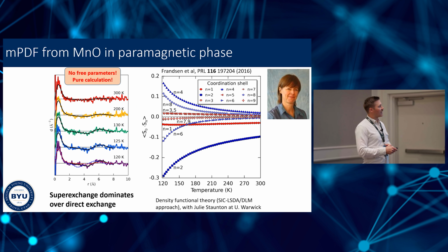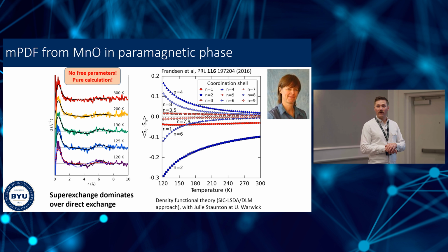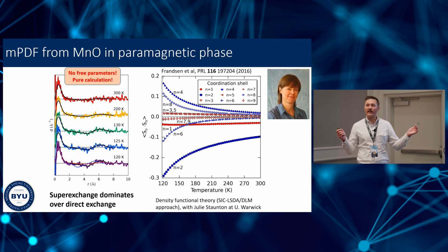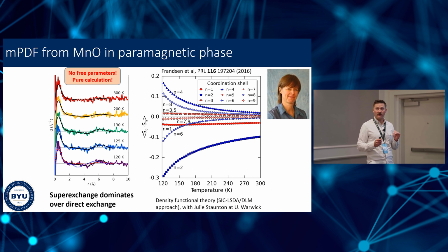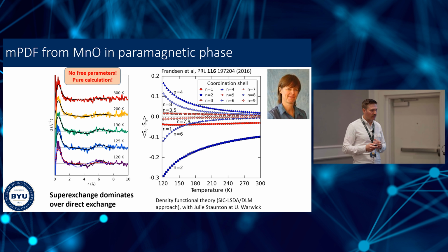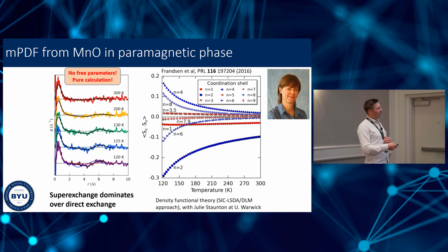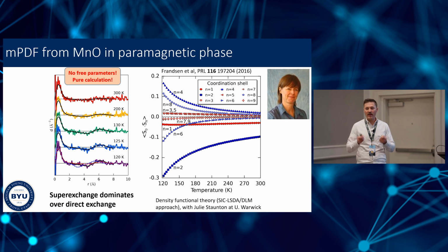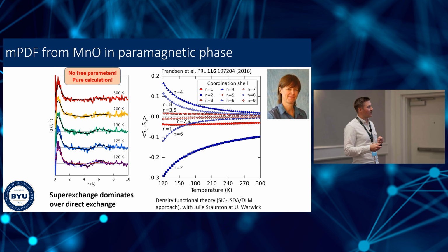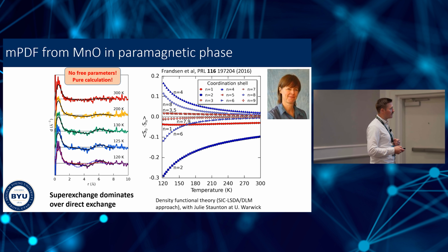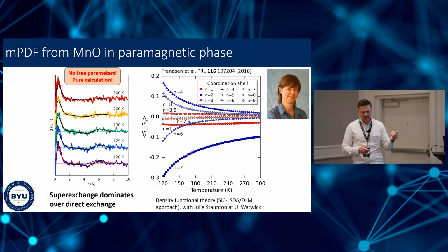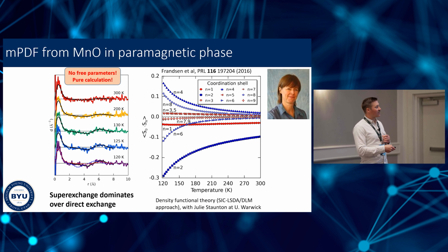But more interesting was to look at the magnetic PDF signal above the Néel temperature, where there were no longer any magnetic Bragg peaks in the scattering pattern. There was magnetic diffuse scattering, of course, because we do have short-range magnetic correlations. But now we can look at those short-range correlations in real space. And so here's the magnetic PDF, these little wiggles going all the way up to room temperature, and I won't go into the details right now, but we could actually learn something interesting about manganese oxide, about the exchange interaction between neighboring manganese atoms. In collaboration with theorist Julie Staunton, we were able to learn something about manganese oxide because we had access to these short-range correlations that persist in the paramagnetic state.